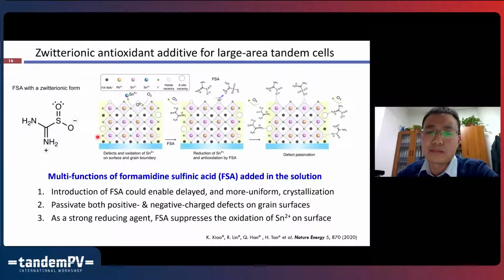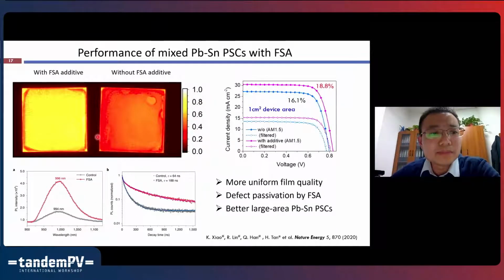We later found that from the PL mapping of the perovskite film over the whole substrate, with this additive we can much improve the film uniformity over the whole substrate. And also we found that the PL emission is stronger with this additive. That is mainly due to the passivation ability of this molecule, and we can also confirm this from the PL decay spectra, because with this additive we get a longer PL lifetime for the perovskite film. As a result, we can increase the efficiency of the 1 centimeter square device from 16.1% to almost 19% for the single junction devices.